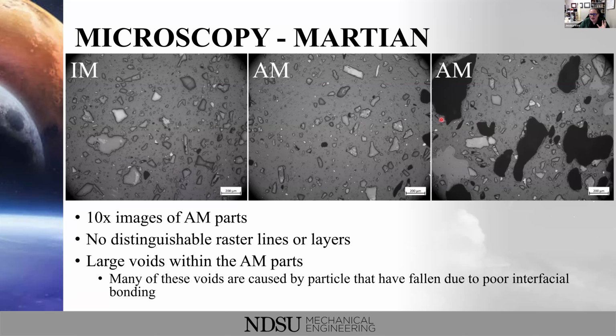And then these other two here on the right are additive manufacturing specimens. What's really, really interesting is to note the voids within them, right? So we have very large voids within this part that we do not see within our injection molded part. You do see some dark, smaller specimens. Those are actually hard minerals that show up dark in our microscopy. So there are no voids within this part. But in our additive manufactured part, these are voids. There is no particle present within those regions of this part.